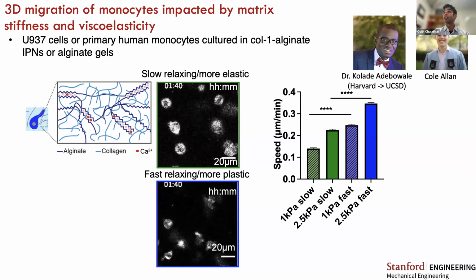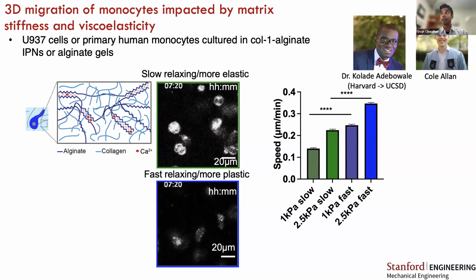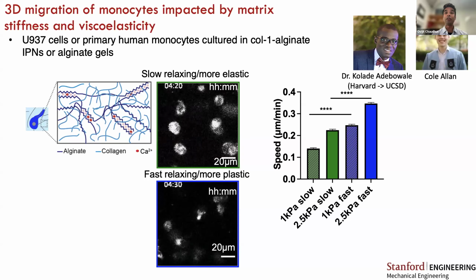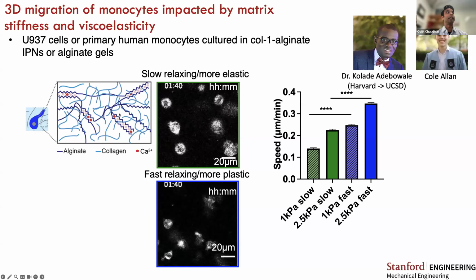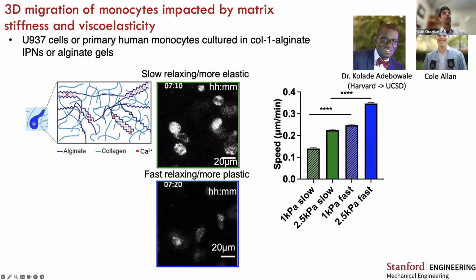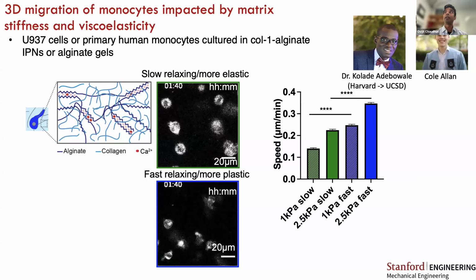So monocytes are immune cells that circulate and then traffic into our tissues where they can differentiate into macrophages or dendritic cells to mediate immune responses. So we cultured monocytes in interpenetrating networks of type 1 collagen and alginate. The idea is that the alginate gives us a handle with which to tune the mechanical properties, whereas the collagen gives us this fibrillar collagen network that is relevant to the stromal matrices that these monocytes will migrate through in our tissues.